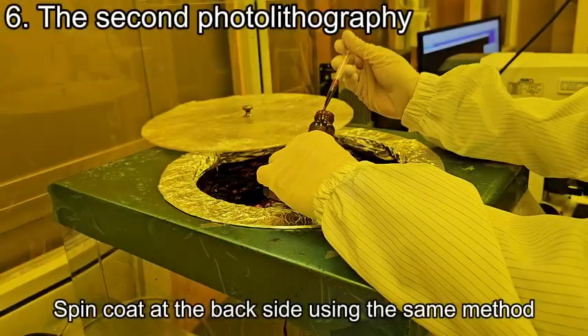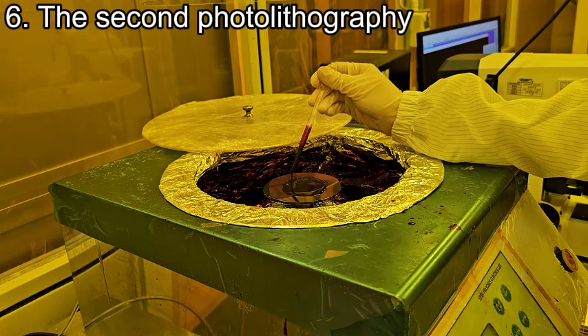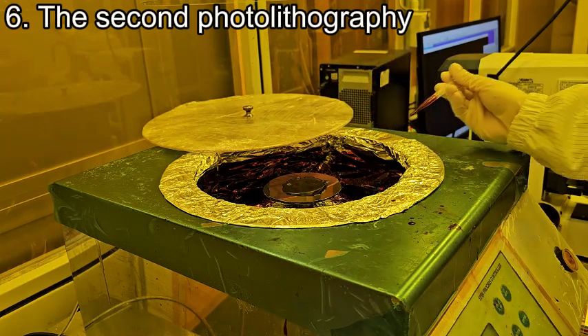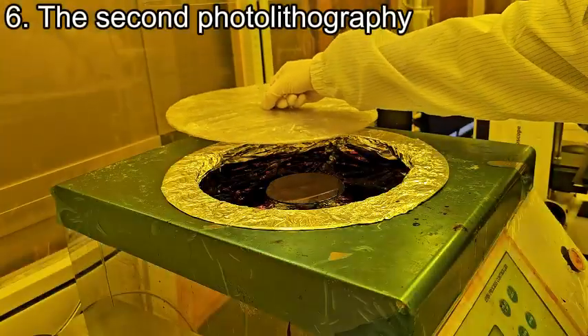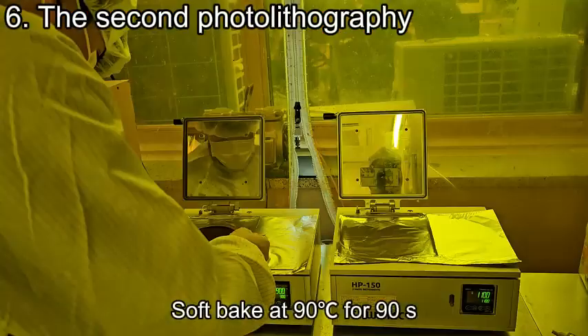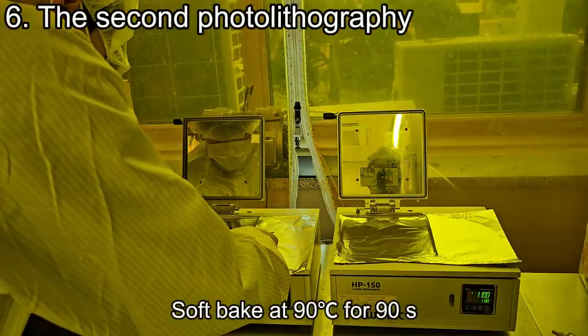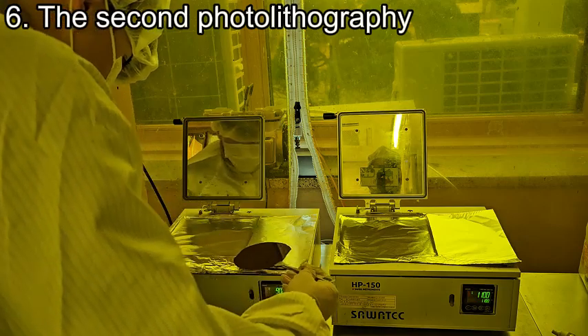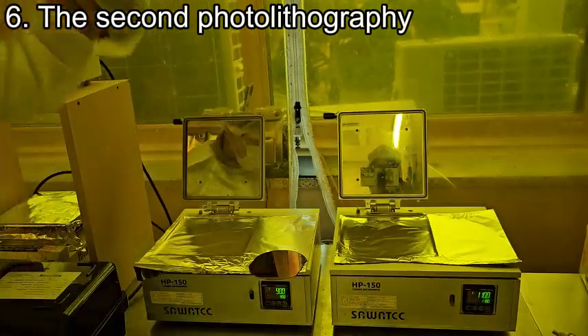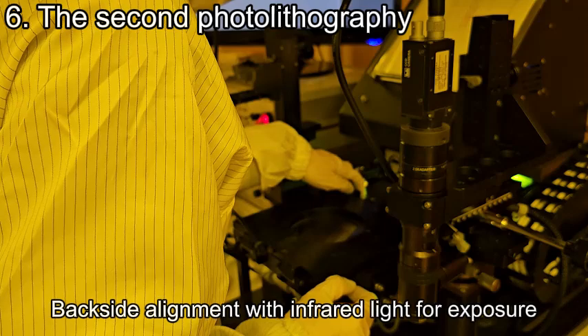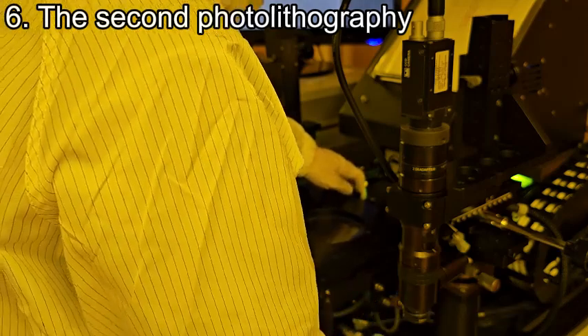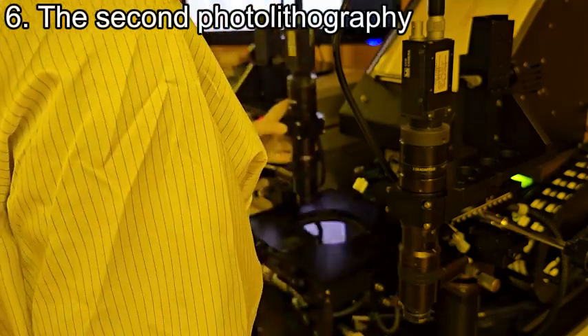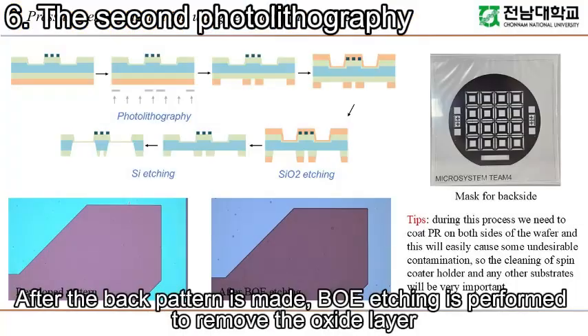Spin coat the back side using the same method. Soft bake at 90 degrees centigrade for 90 s. Backside alignment with infrared light for exposure. After the back pattern is made, BOE etching is performed to remove the oxide layer.